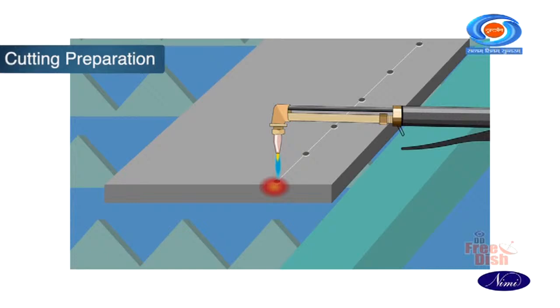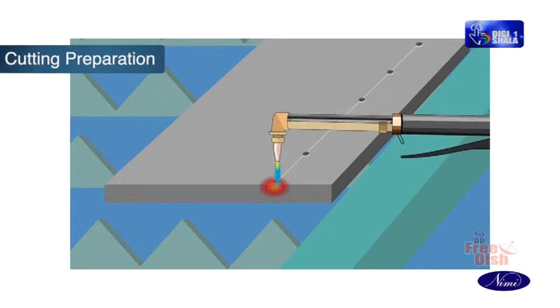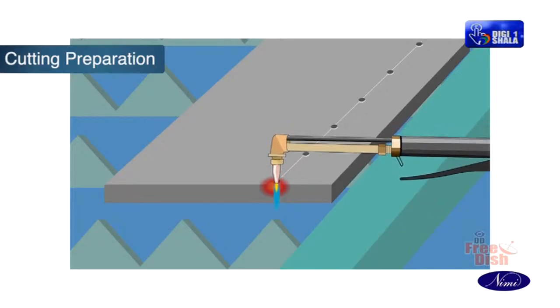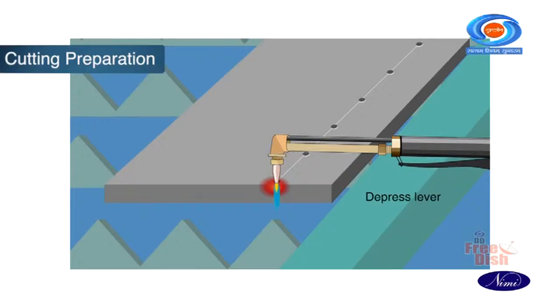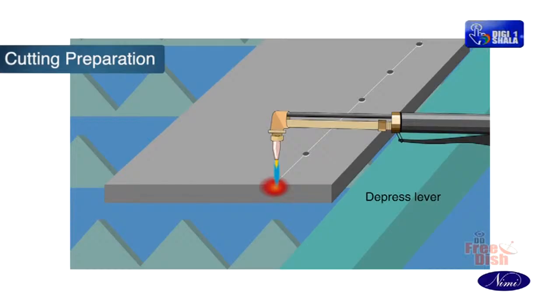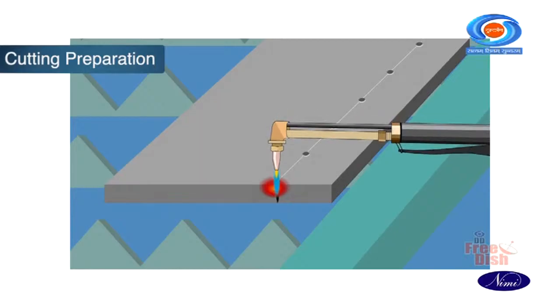When preheating the starting point of the cut, hold the torch tip close to the surface of the plate. When the metal is hot enough, slowly depress the cutting lever and raise the torch to avoid blowing slag back onto the tip. When the plate has been pierced completely, lower the torch.